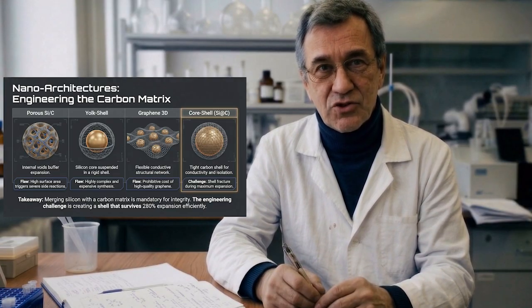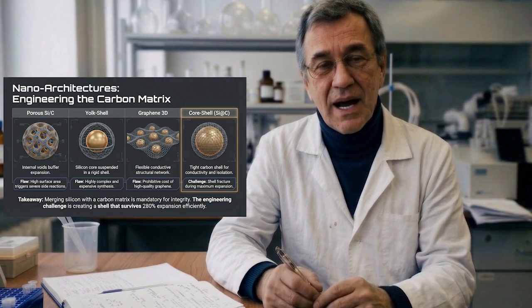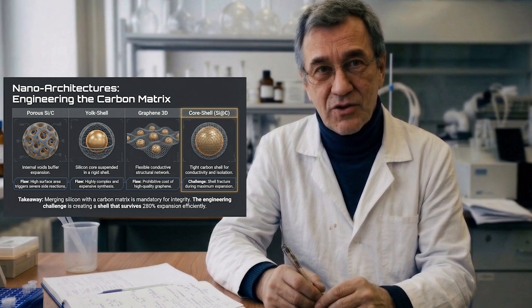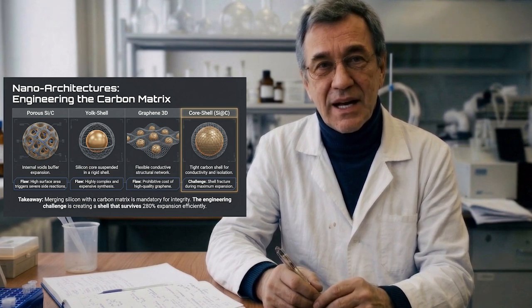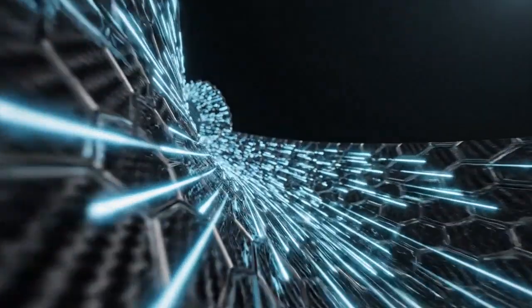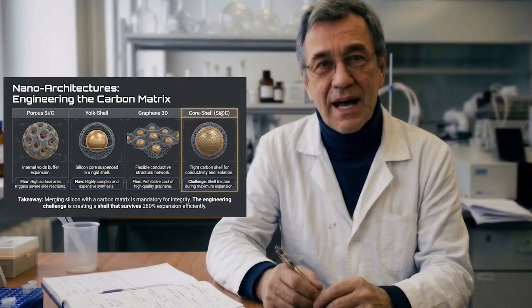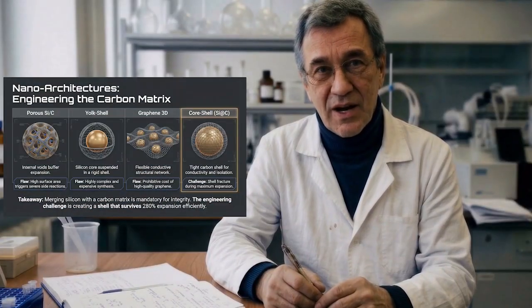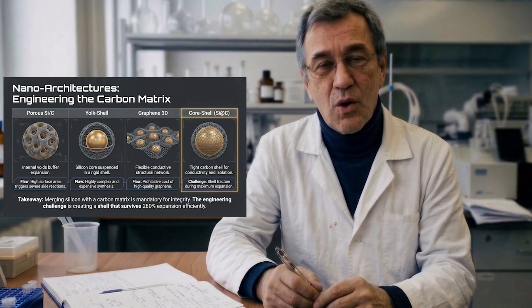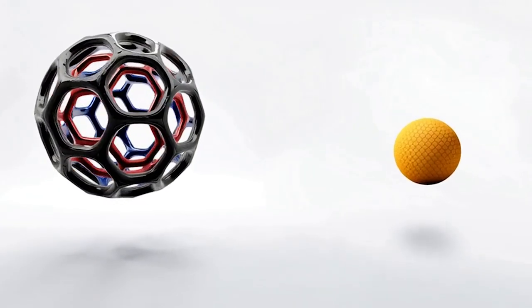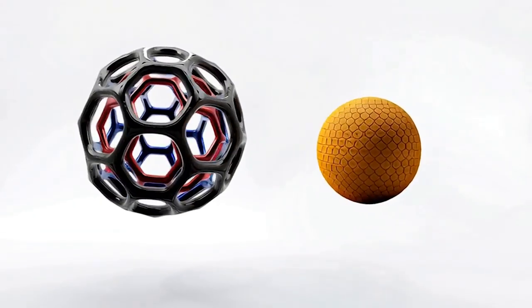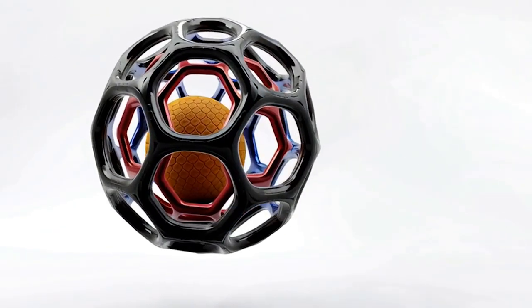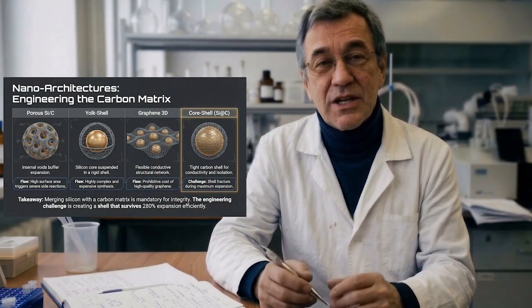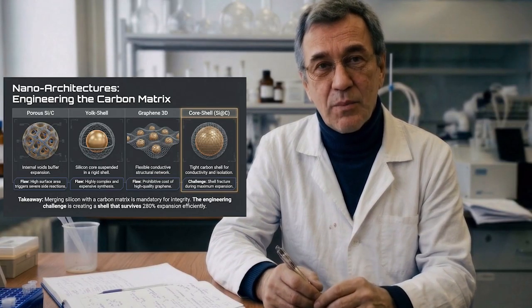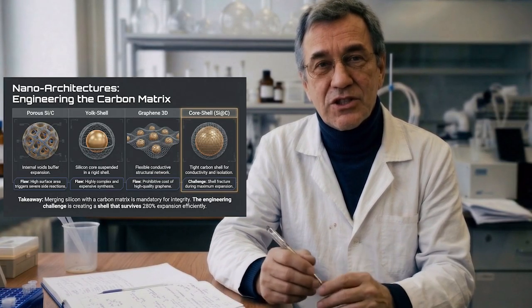One of the most effective strategies is to create a composite by combining silicon with a carbon matrix. Carbon can act as a mechanical buffer and a highly conductive highway for electrons. Our patented method uses pyrolysis to create a core shell structure, what we call silicon-carbon. Here, a silicon nanoparticle forms the core, and it is uniformly coated with a thin, robust shell of carbon, specifically graphene layers. This is not just a simple coating. The carbon shell forms a conformal layer around the silicon core.